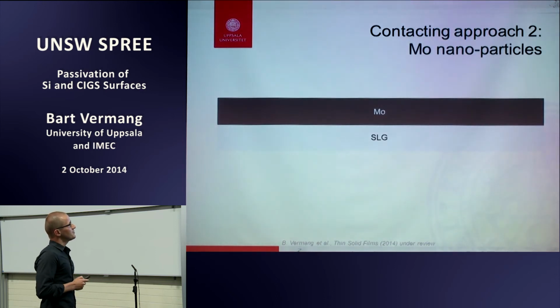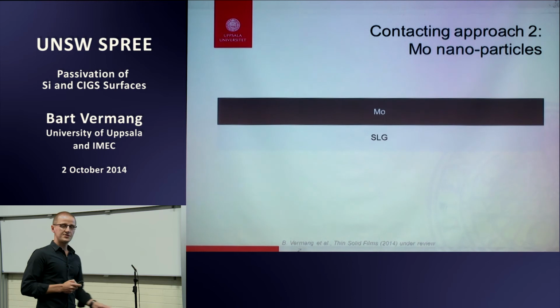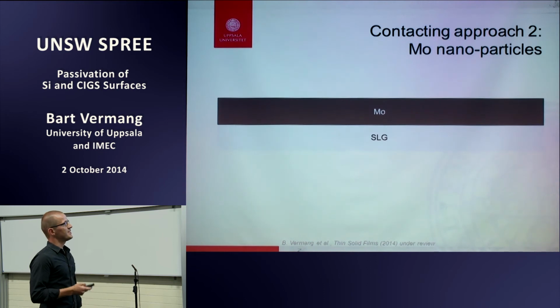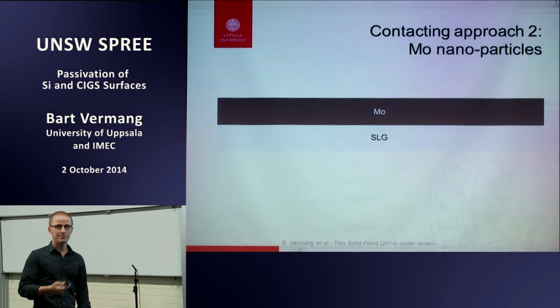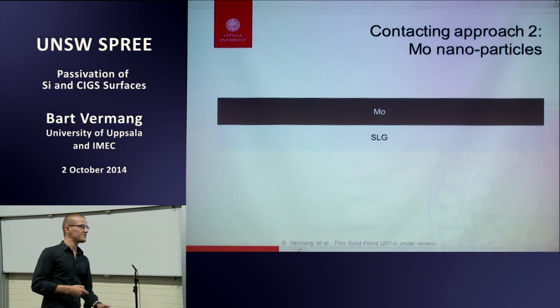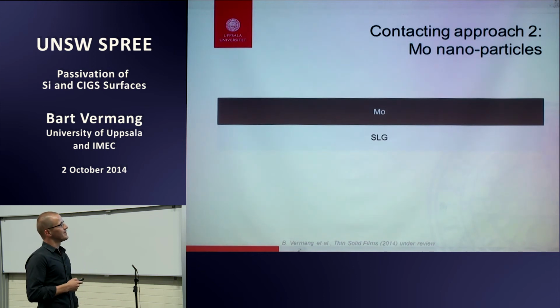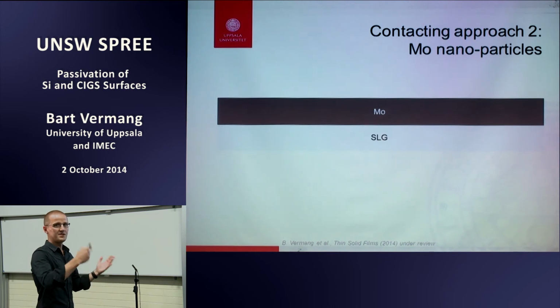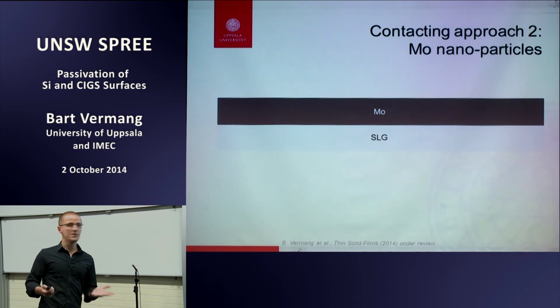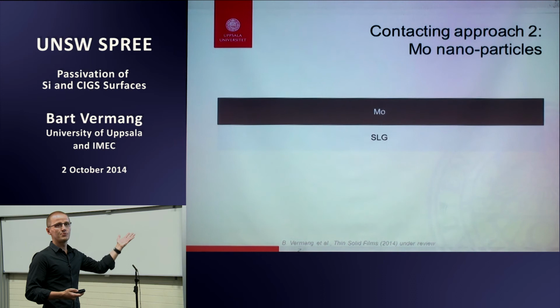The second approach we used was molybdenum nanoparticles, so conductive nanoparticles, so that we could leave them over there. One of the disadvantages, or why we chose molybdenum, is that if you would use another metal, it might become fluid or liquid during CIGS growth, or you might even start to diffuse it into your CIGS layer. Plus, it needs a good contact, and we know at least molybdenum is being used as a contact, so molybdenum nanoparticles should also give a good contact.